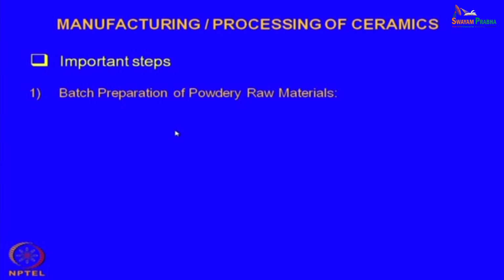As I mentioned earlier, our starting material is always powders. It is not lumps; even if lumps are available, they have to be ground to a very fine powder. Since in most cases ceramic materials have a high melting point, melting is always avoided, because it is a very high temperature process and it is not so economic, but we start with powders. At the same time these powders must be consolidated enough, so that at the end of the fabrication process, you do get a geometrically sound, mechanically sound material.